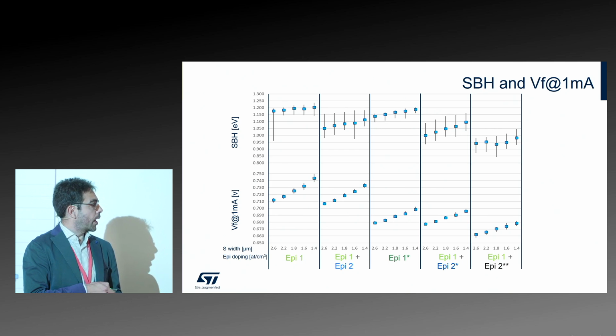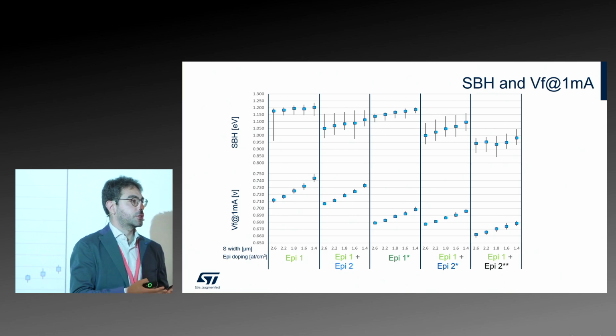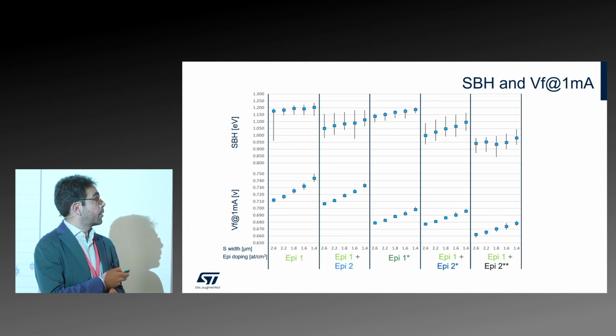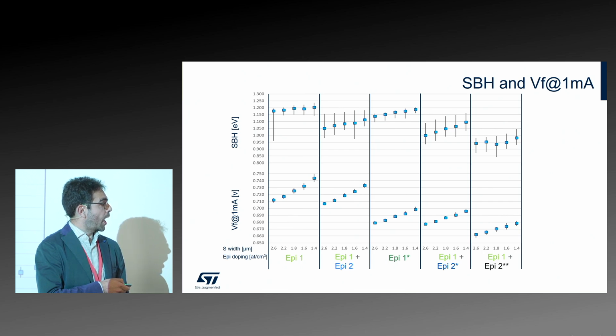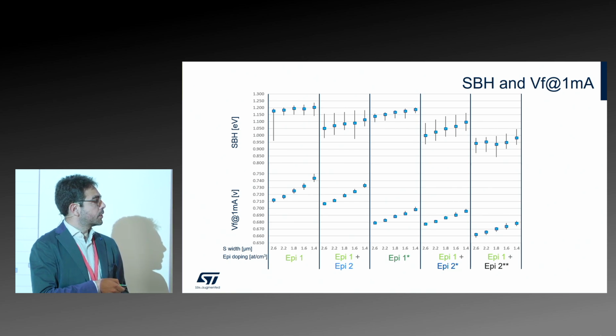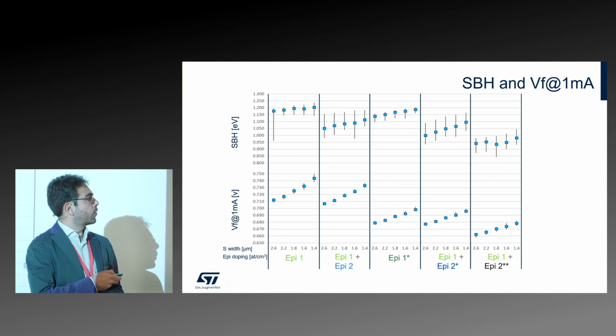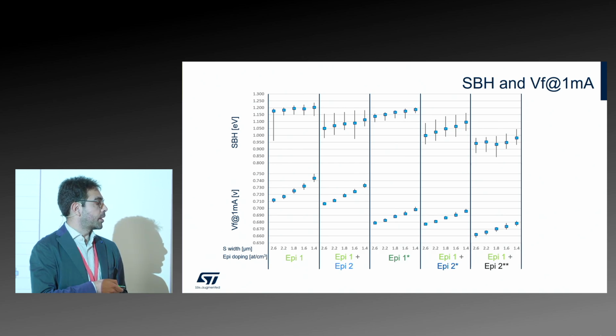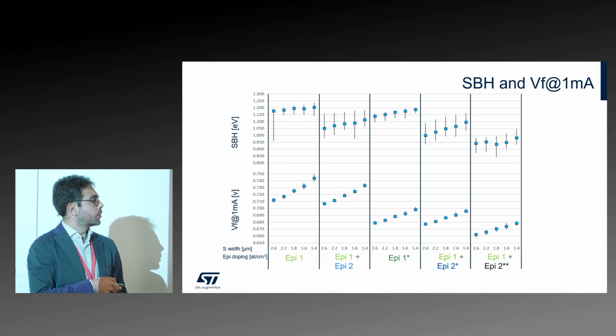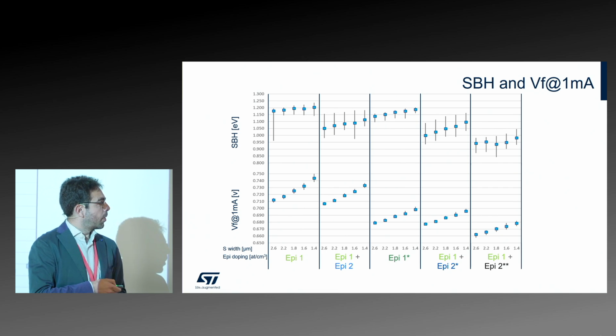But if I take the epi 1 and dope it by implantation, so I just changed the doping in a different way, again, the barrier height remained the same, but the VF dropped down abruptly. And again, with the pinching effect, I can modulate my VF. Following this, with epi 2, the barrier height falls down because of the doping of epi 2, and then by the channeling, by the implantation, also the VF is very low. And if I double implant the epi 2, again, I observe a drop down of the VF. But what is interesting to me is that I can span from 0.74 as VF at 1 milliamp to 0.66. So a quite huge range in a very controlled way.